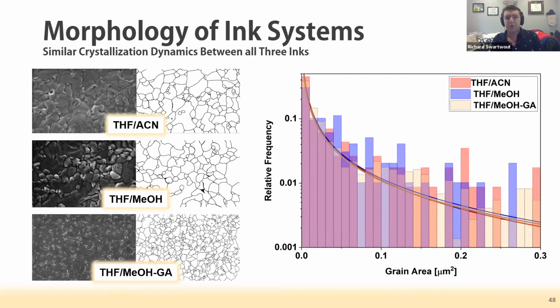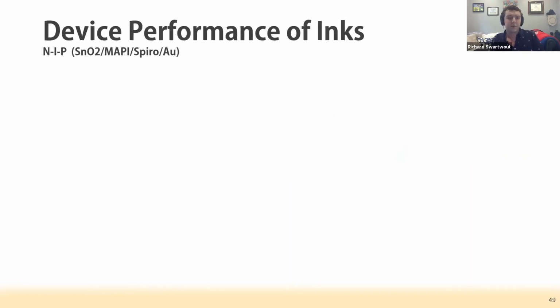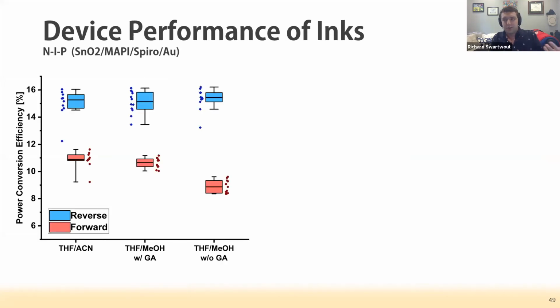This is further reinforced if we make devices from these inks. In a traditional NIP structure of tin oxide, methylammonium lead iodide, and spiro, we can also show the device statistics of forward and reverse scans. They're a little hysteretic, but again, I want to emphasize that the key takeaway here is that they're all the same, not that they're highly optimized at being highly efficient.